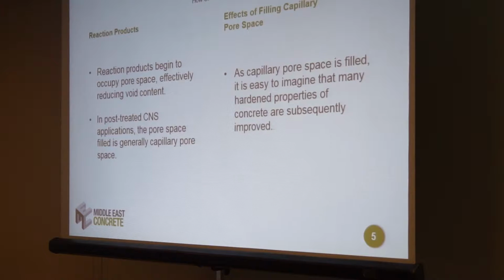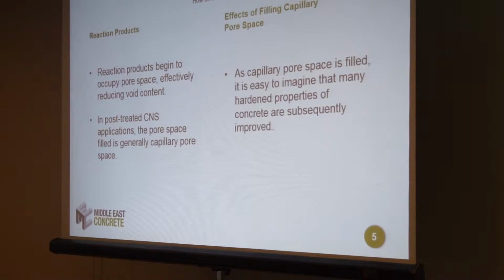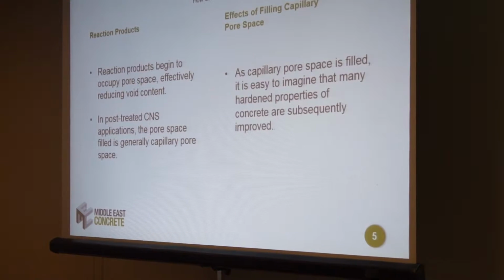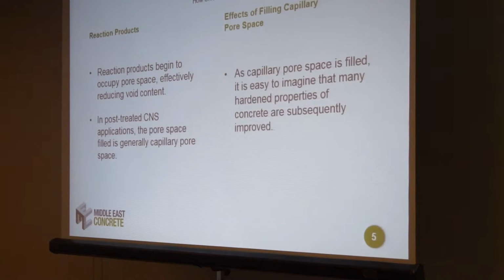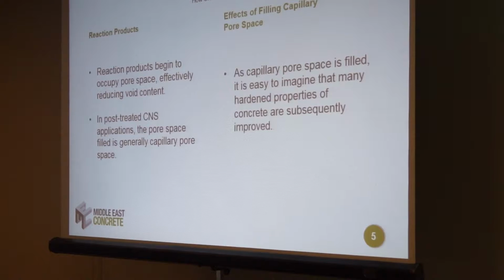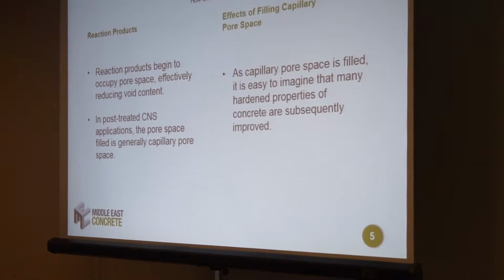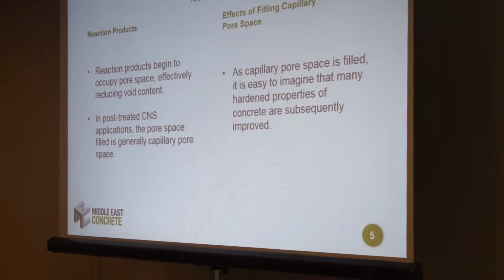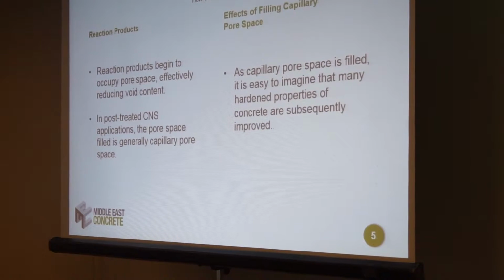So the primary filling mechanism, from the literature review, is that pozzolanic reaction we were talking about. It's taking calcium hydroxide, reacting with it and forming more calcium silicate hydrate, which begins to fill that capillary void space. So if you think about it carefully, if you reduce the amount of void space in the concrete, then there are a lot of hardened properties that are likely to improve. We're going to take a look at those.